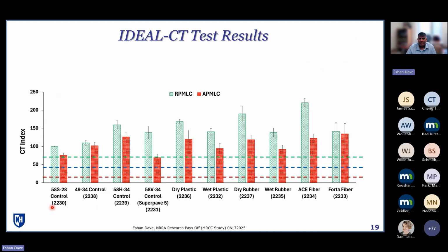In terms of the ideal CT or CT index, once again, two sets of bars for each of these mixtures. Green represents the reheated plant mix, lab compacted. Red represents aged plant mix, lab compacted. So it went through that 6 hours of loose mix critical aging at 135 degrees Celsius.